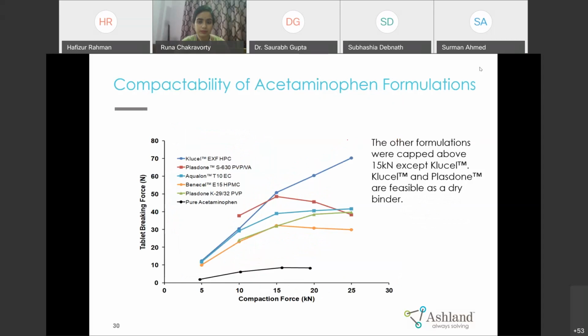Now coming to acetaminophen, which is having poor compressibility. So again, we compressed tablets at different compression force, and we checked the tablet hardness. And we found that tablets containing Klucel give us the strongest tablet at all the compression forces. Especially, you can see the difference on the tablets which were compressed at higher compression force, and there was no capping observed. So you can say that irrespective of API properties, whether it is hydrophilic or hydrophobic, whether it is compressible or poorly compressible, if we are going with direct compression, then Klucel EXF gives us better hardness when compared with other binders.